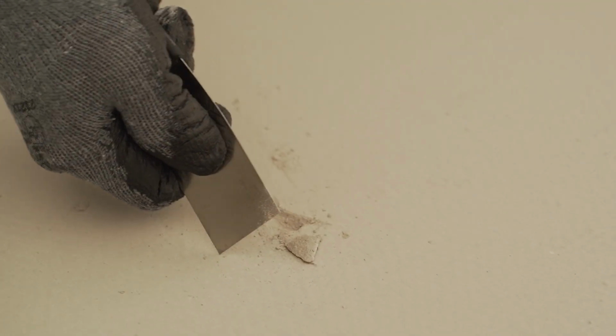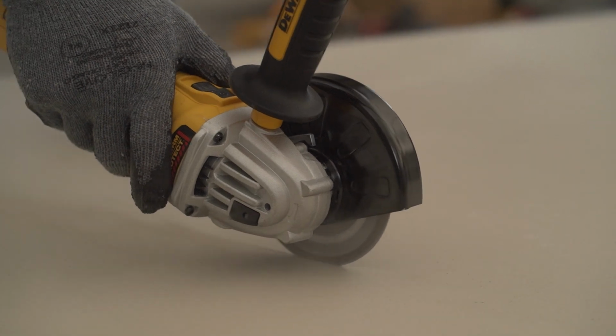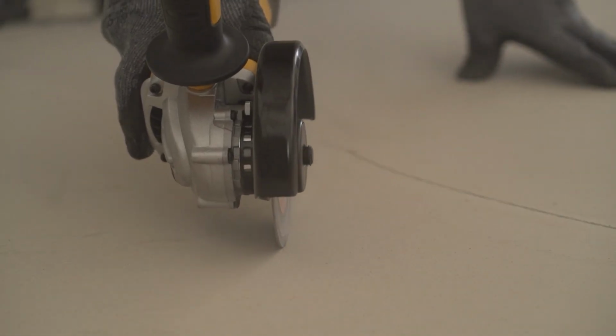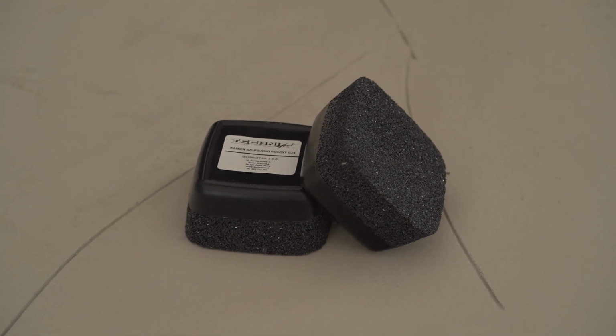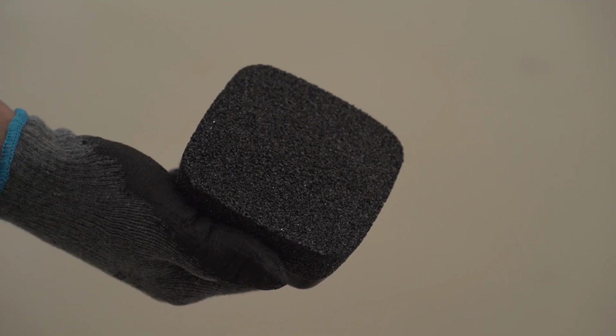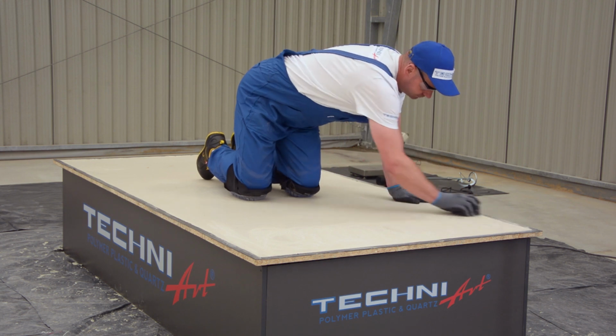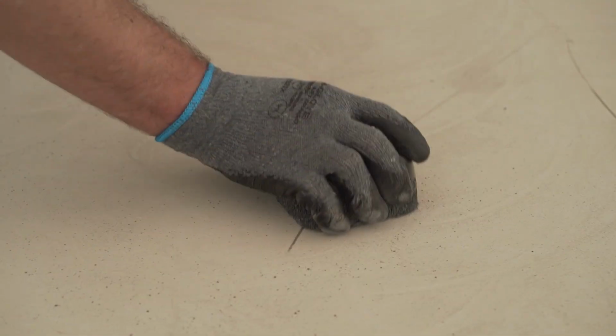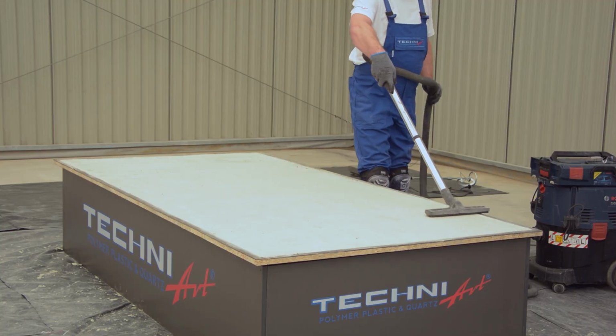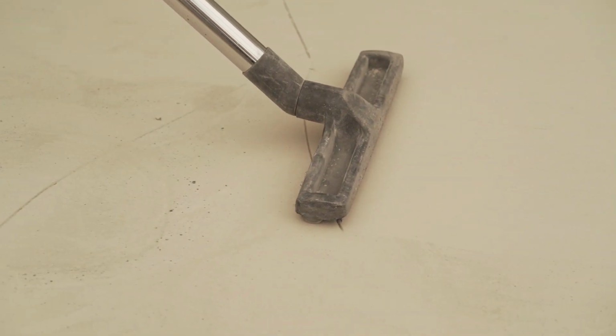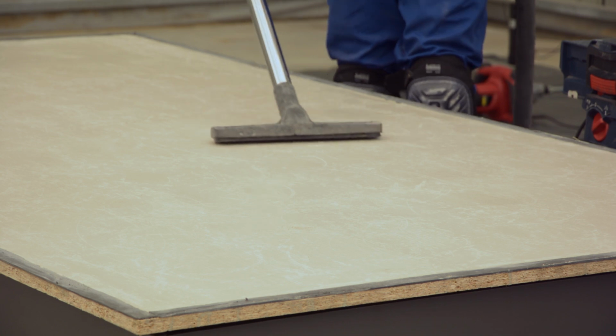As we have already said, in this video we demonstrate the execution of a floor on a worn, uneven, cavity and cracked substrate. In such a case, work should begin with the removal of loose, detached elements of the substrate. Then score any cracks with a diamond disc. Then, the substrate should be ground with a concrete abrasive stone. After grinding, the whole thing should be thoroughly vacuumed, remembering to use a narrow suction nozzle to clean the cut slits.